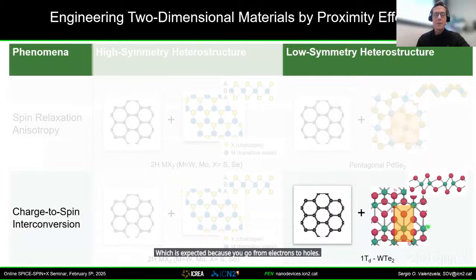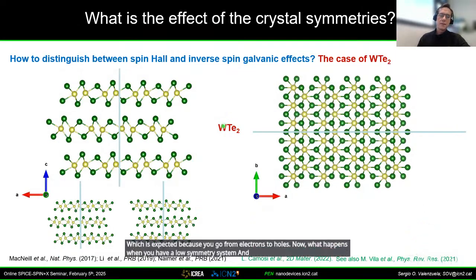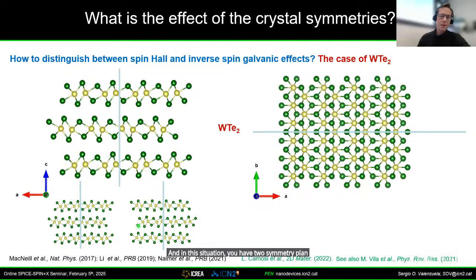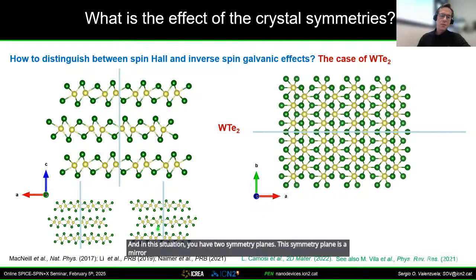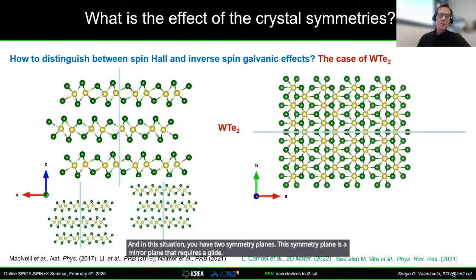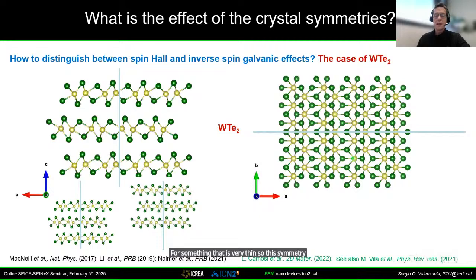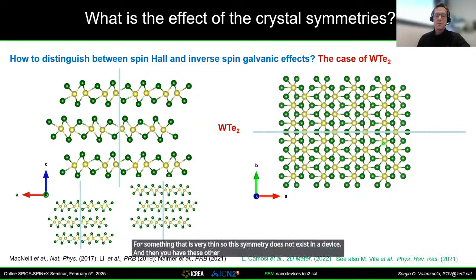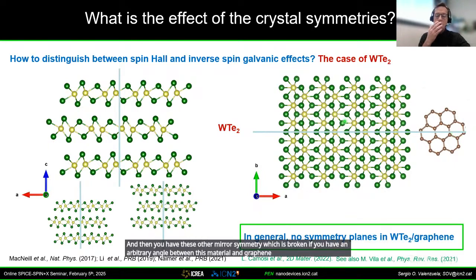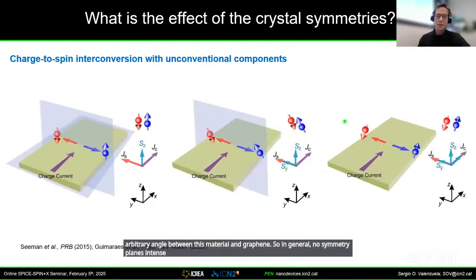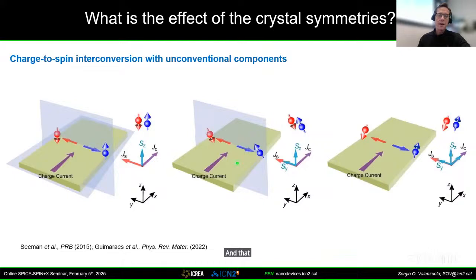Now, what happens when you have a low symmetry system? In this case, we picked tungsten ditelluride. In this situation, you have two symmetry planes. This symmetry plane is a mirror plane that requires a glide, which is represented here. Because of this, it is actually a symmetry that you have in the bulk, so it doesn't matter for something that is very thin. So this symmetry does not exist in a device. And then you have this other mirror symmetry, which is broken if you have an arbitrary angle between this material and graphene. So in general, no symmetry planes in tungsten ditelluride graphene, and that implies that you can have any components for a spin Hall effect.